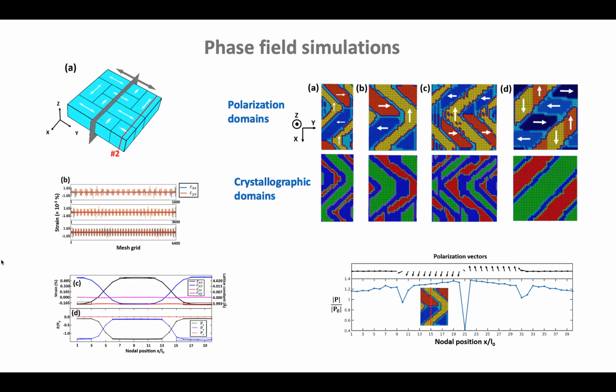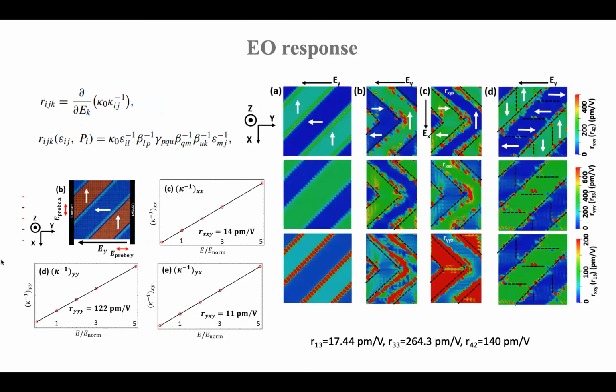And so we go through the whole simulation cell. We average out the values. We get the strain. And then we figure out what the lattice constant is, and we assign the phase. The Hamiltonian actually is fitted to reproduce the barium titanate phase diagram. It's not fitted to produce electro-optical response, right? But that's what we're actually interested in.